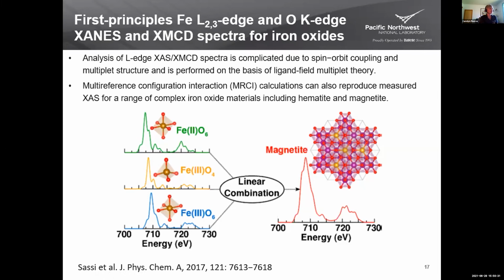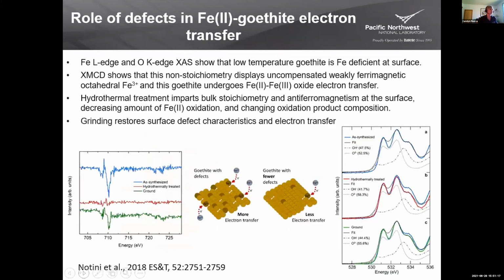So this is some really nice work by Michel Sassi to be able to interpret the iron L-edge XAS and XMCD, as well as the oxygen K-edge XAS from first principles, using high-level quantum chemical methods, which have some advantages over previous ligand field multiplet models, which were traditionally used to fit these data. And they have some downsides in terms of the empirical parameters that you have to use to best fit the experimental data, especially if you're looking at systems where the ligand field changes. And so these quantum mechanical methods allow us to remove the need for those empirical parameters and really understand what the spectrum is telling us by relating it directly to the structure.